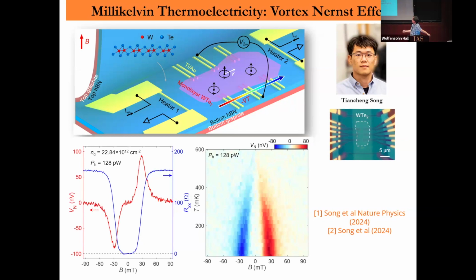For example, I can apply a magnetic field in the perpendicular direction so that I can tune the superconducting state to the normal metal state—a magnetic field induced transition.